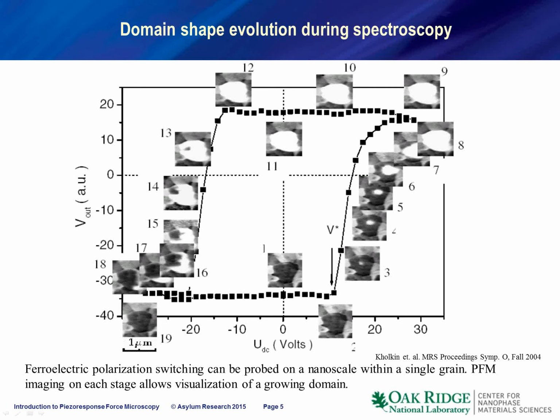For small biases, in this case from 0 to about 10 volts, nothing happens. We have this central grain, which remains absolutely black. At this nucleation bias, we start to form a white grain, and this grain grows with increasing bias. Notice that the grain continues growing, but the response saturates because the tip is sensitive only to what is below the tip. It's not sensitive to the parts of the grain very far from it. On applying the bias in the reverse direction, nothing much happens, and then at negative biases, we start to see the formation of the black domain. So there is a very good correlation between the hysteresis loop shape and the domain shape.